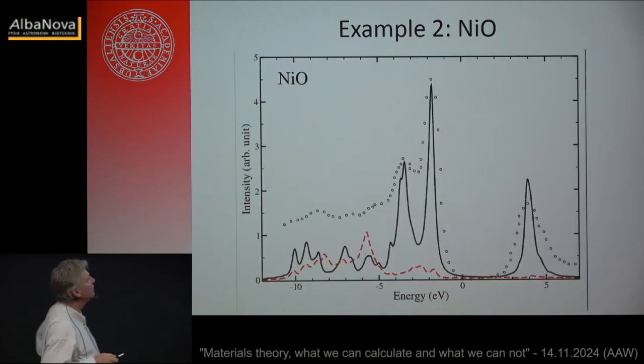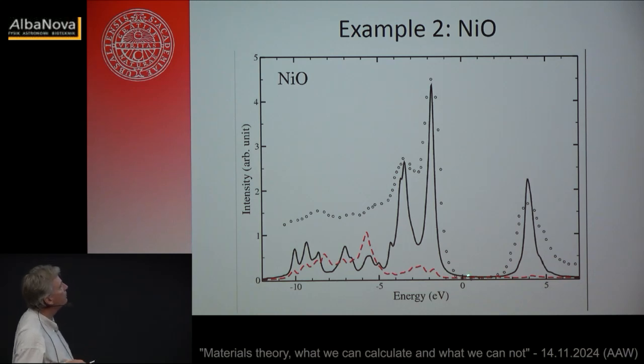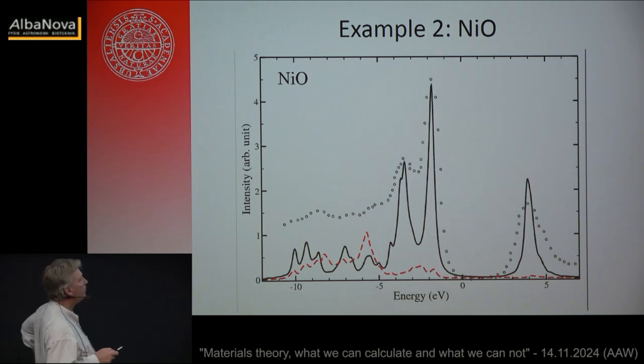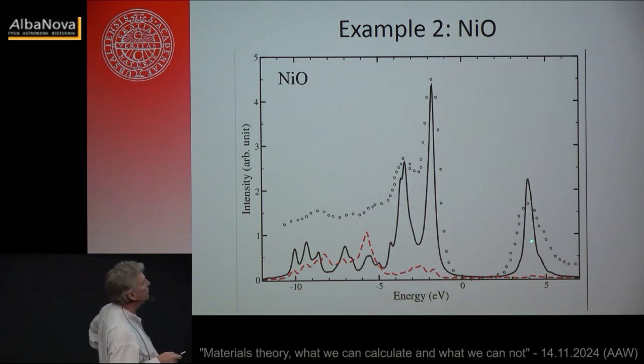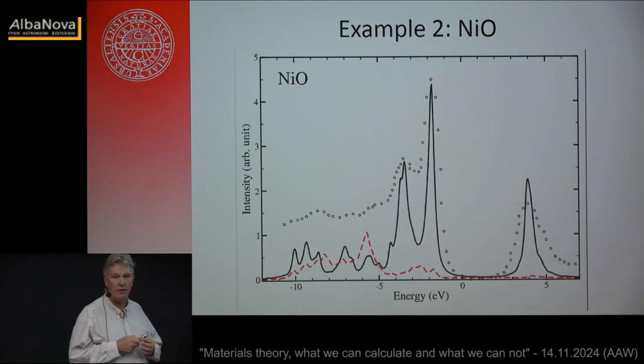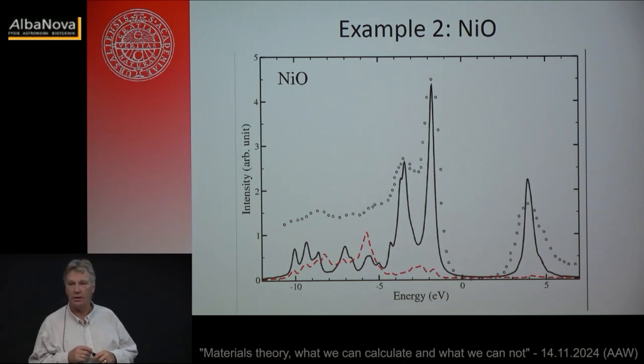Nickel oxide is another one. So here are now measurements of inverse photoemission, that's this graph here above 0, and photoemission, XPS, these points, round circles here. And theory now is the solid black line. Nickel d orbitals is black, and oxygen p is red. And the sum of this actually starts to look pretty good, and a pretty good agreement with experimental data.